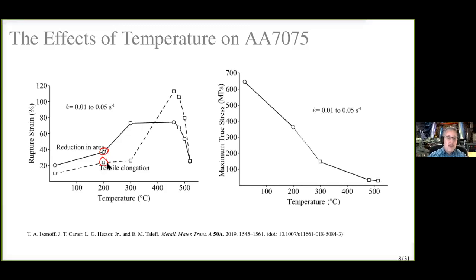So here we can get a significant increase in ductility, and we don't have the material being too far above the aging temperature, which was about 120 degrees Celsius here. So we may be able to somehow fix the heat treatment to not lose all of our strength from the T6 condition. If you go to high temperatures, we of course get much better ductility, but then we have all the issues I talked about with hot forming. Once you get to temperatures down here of about 450 or so, you start to get a decrease in ductility because of cavitation and rupture issues, which I won't go into today.